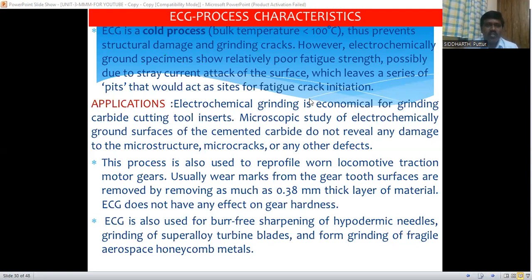Now coming to the applications, electrochemical grinding is economical for grinding carbide cutting tool inserts. A microscopic study of the electrochemically ground surface of cemented carbide does not reveal any damage to the microstructure, micro cracks, or any other defects. This process is also used to reprofile worn locomotive traction motor gears. Whatever damage has happened to the traction motor gears used in locomotives, those worn places can be reprofiled by this process. Usually the wear marks from the gear tooth surface are removed by removing as much as a 0.38 mm thick layer of material, and this process does not have any effect on gear hardness.